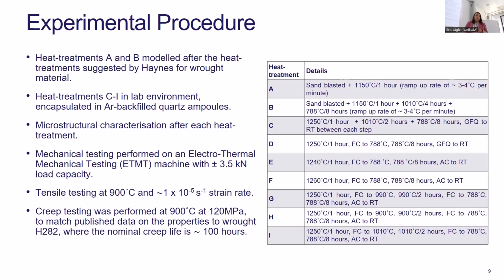We did some microstructural characterization after each of these steps, and we did the mechanical testing on an electrothermal mechanical testing machine. Effectively, we tested tensile at 900 degrees Celsius at 10 to the -5 strain rates, and we did some creep testing that we tried to get about 100 hours lifetime from, so we were using data from the existing literature. So that was 900 degrees Celsius at 120 MPa.